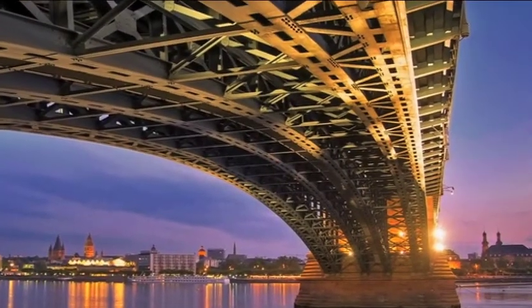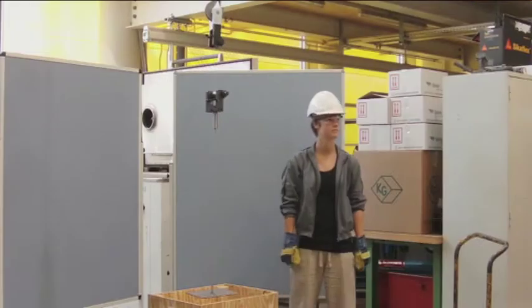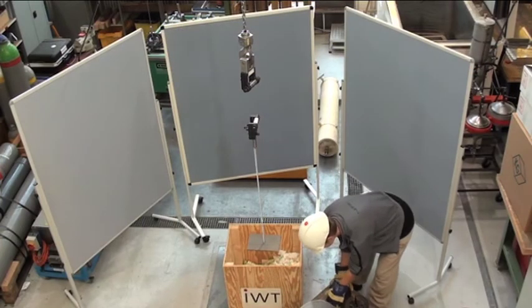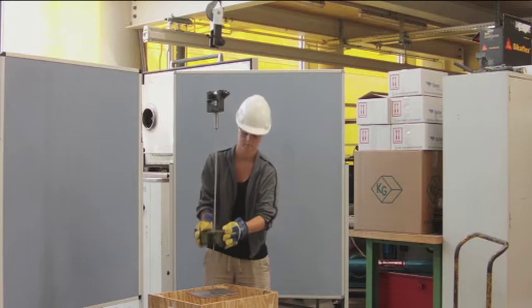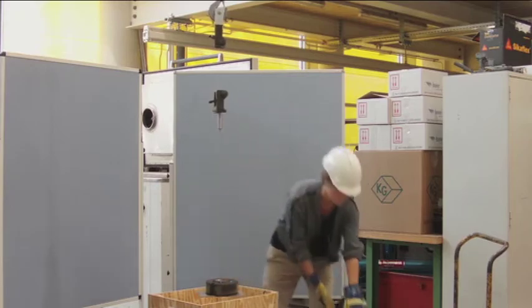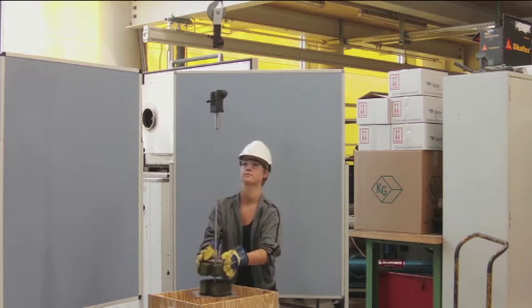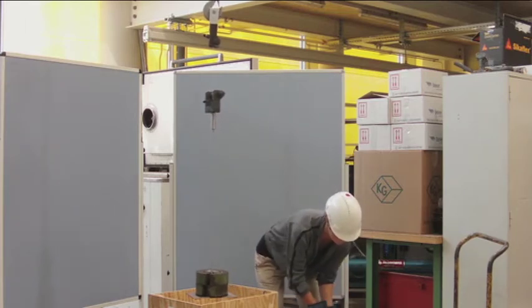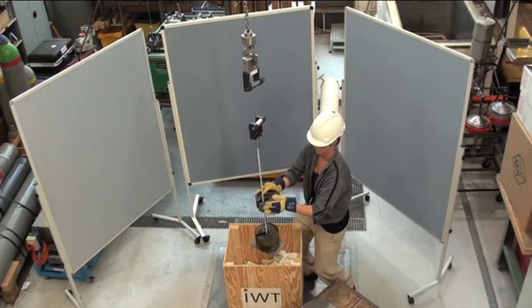Steel is not a uniform material. The differences between individual steel grades are sometimes enormous. To verify this, we load steel wires with an identical cross-section of 1 square millimeter each with weights. Both materials are unalloyed except for a slightly higher carbon content of the second wire. The first specimen is a soft material suited for uses such as florist's wire. To achieve this, it was heat-treated at high temperature followed by a slow cooling process. This made it soft. The wire already fails when subjected to a load of just 32 kilograms.